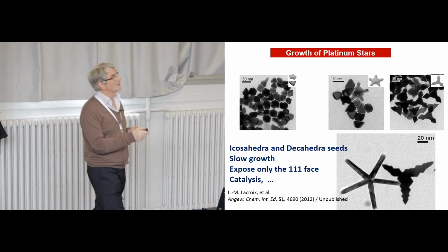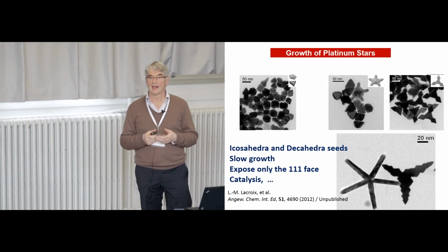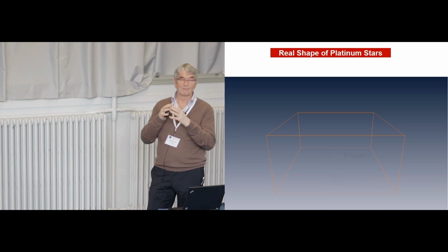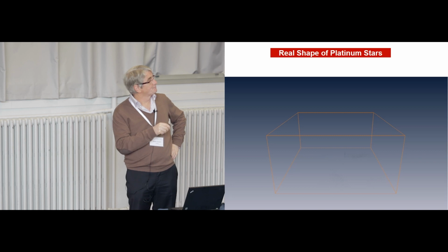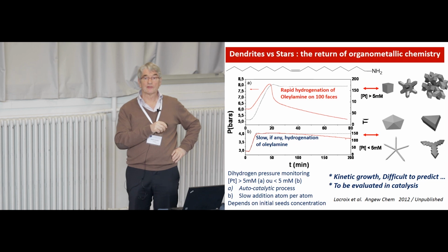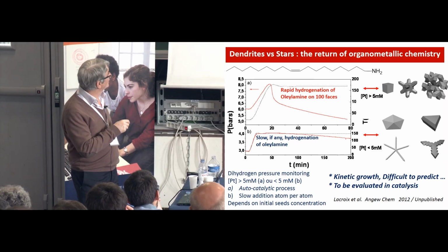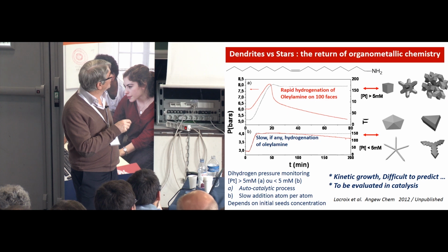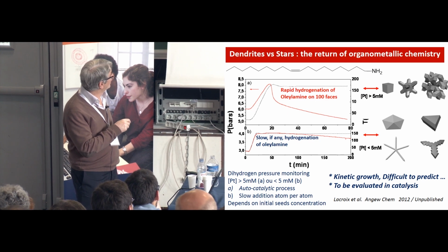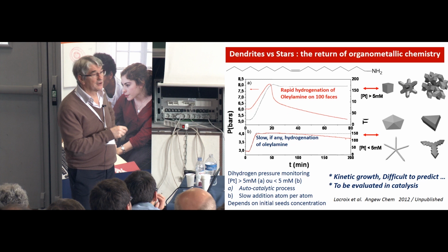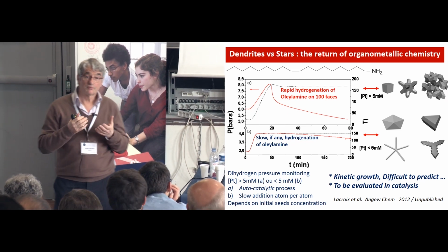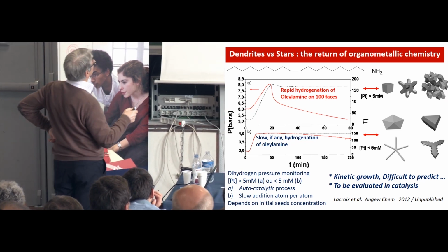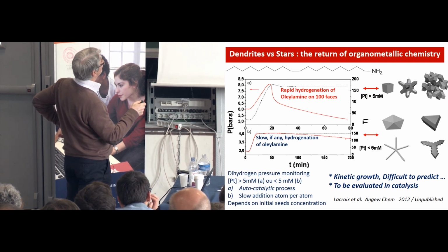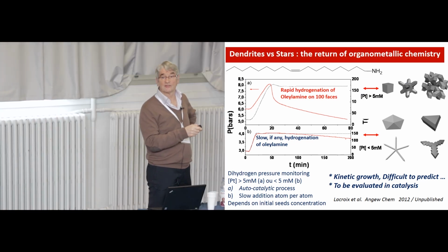And it's where organometallic chemistry returns. Why is that? It depends on the concentration. What we could see is that if we work with a low concentration of platinum, the hydrogen uptake is very small - this is the hydrogen uptake shown in red. So it's very small, and in fact it corresponds to slow decomposition. But at high concentration, we have a lot of hydrogen uptake in the solution.